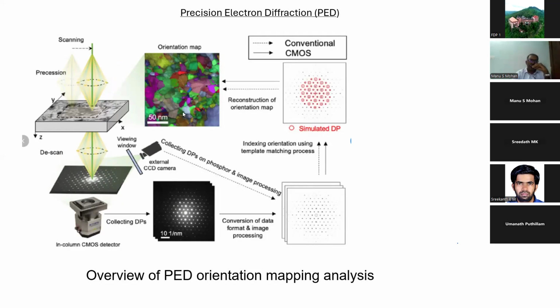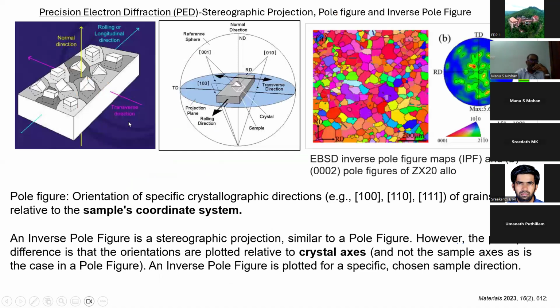So here it is more of a TEM-based EBSD. I used to say to my friends that it's more like a TEM-based EBSD. They also produce the orientation map. So how it works is, you have the electron beam, you spin it around the axis, you basically cause the Ewald sphere to revolve around its axis. Therefore, you get more patterns. Kinematic diffraction is satisfied. You are able to record a much higher number of reciprocal lattice points.